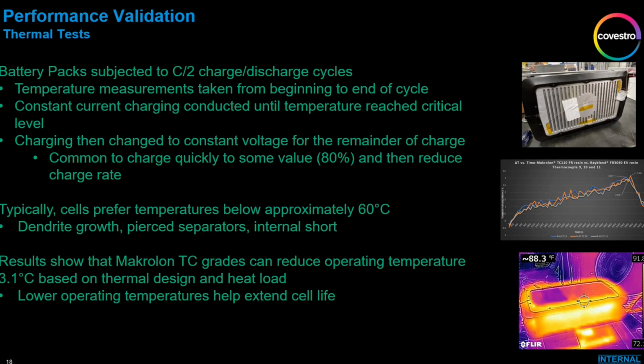And if you remember, most batteries do not like temperatures above approximately 60 degrees Celsius. They start to have issues. So temperature control in a pack, I don't think I need to explain, is pretty critical. And the net result was, over the charge discharge cycles that we ran, we saw a 3.1 degrees C cooler operating temperature with the Makrolon TC grades versus the non-thermally conductive grades. So you do see a performance improvement there from the thermally conductive material.